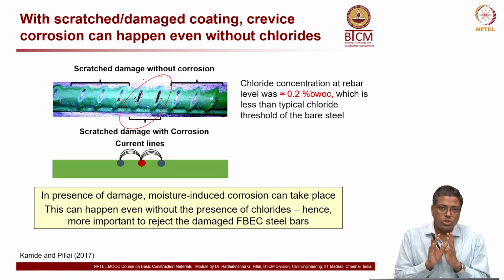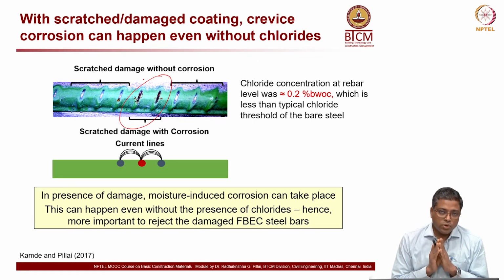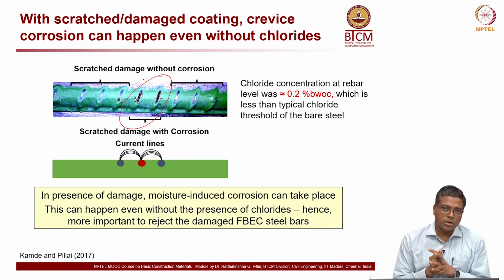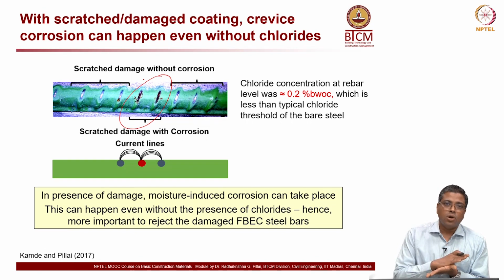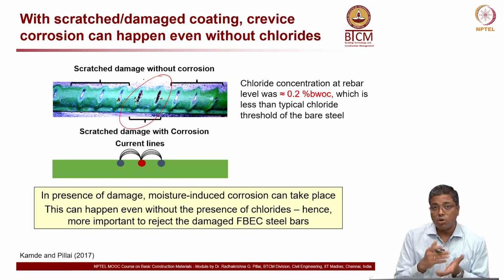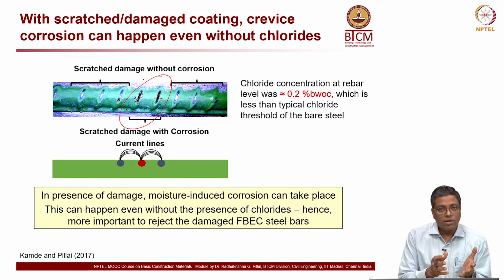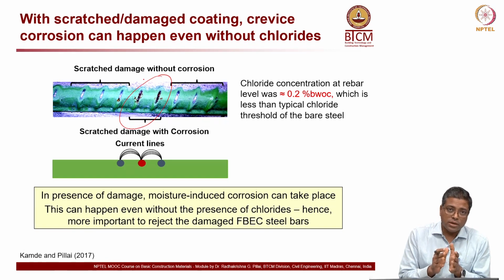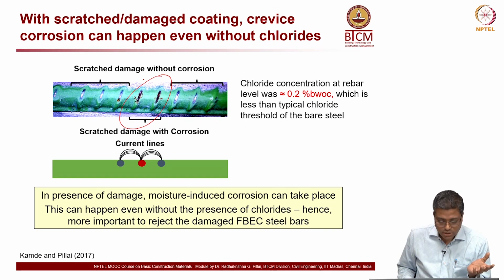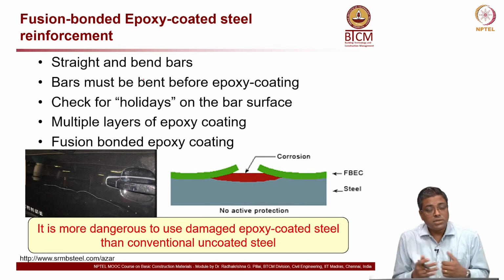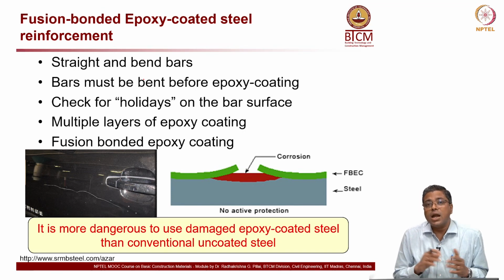The point you have to understand today is that if you use this non-metallically coated rebar, there could be scratches or cracks in the epoxy coating which may or may not be visible to the naked eye, and some of those cracks or scratches will start corroding while others will help the other scratches to corrode. This is going to happen even without sufficient chlorides. So, it is more dangerous to use damaged epoxy coated steel bar than an uncoated steel.